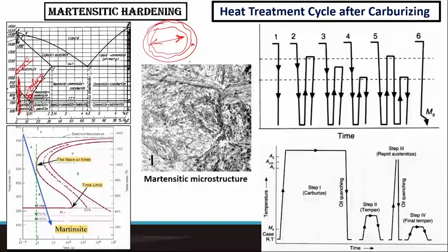In order to do that, we can't convert at room temperature. So we have to heat to a temperature above the austenitizing temperature, typically AC3 for the hypoeutectoid range and AC1 for hypereutectoid composition, and then we quench. When we quench, we have to ensure that we are quenching at a rate faster than the critical cooling rate, so that we can avoid the nose. This is an important thing. Once we do that, we end up with this martensitic aggregate. And this martensitic aggregate, please remember, not only has martensite, but may also retain some retained austenite. The lower the amount, the better it is. But 100% martensite is practically impossible because of variation of depth and the corresponding cooling rate variation. So typically we can go through various kinds of carburizing cycles, which essentially is to expose to high temperature above AC3 primarily.